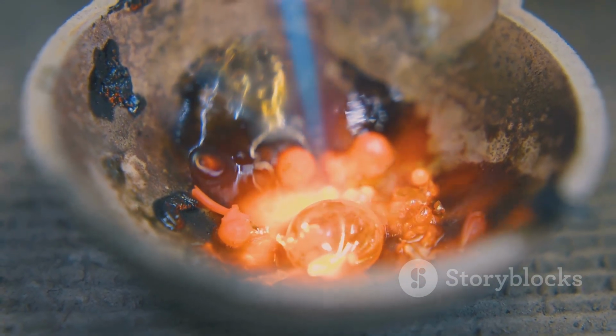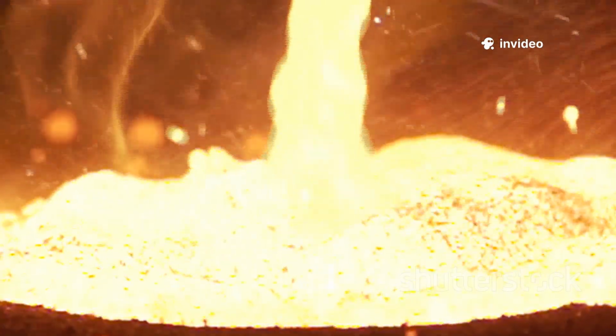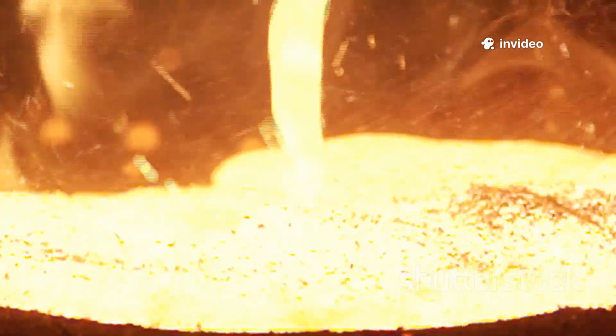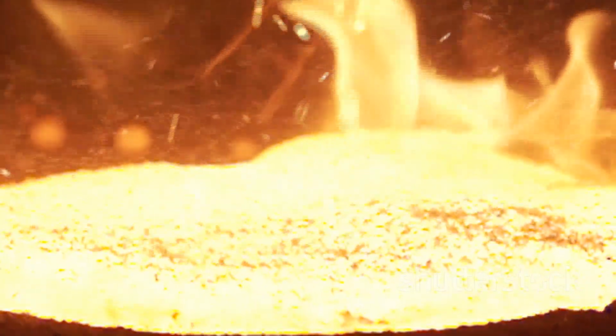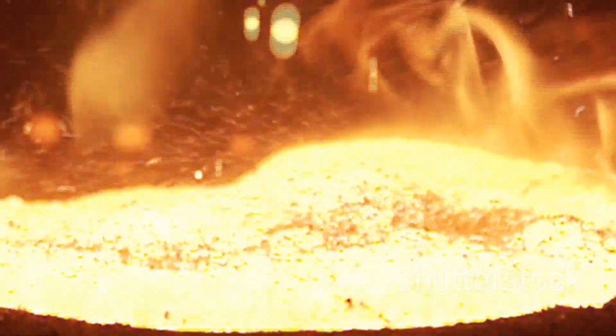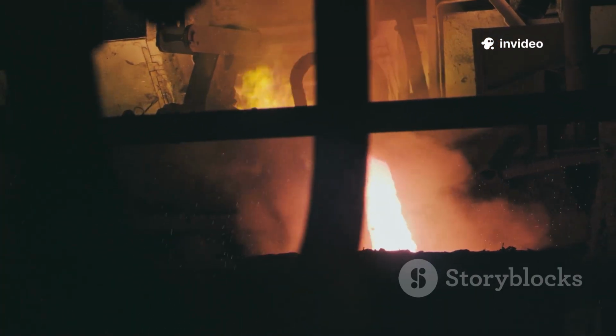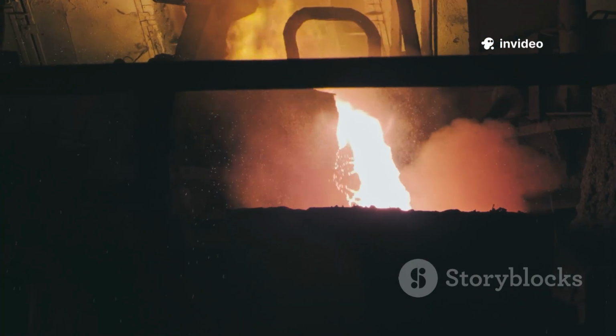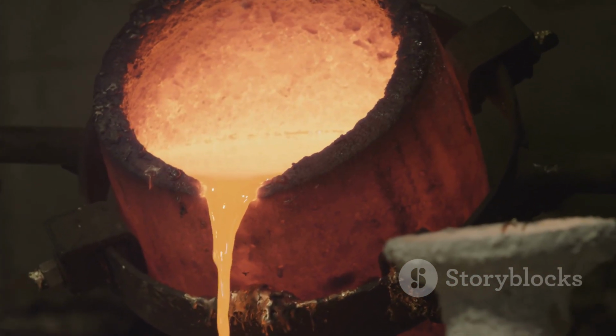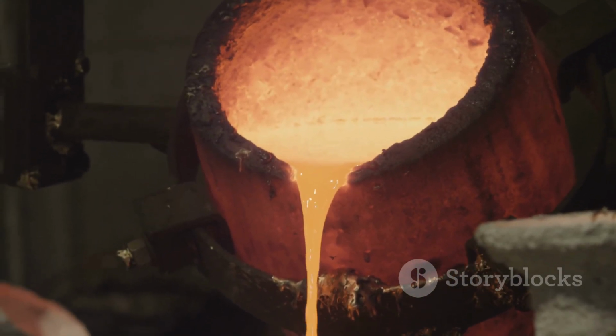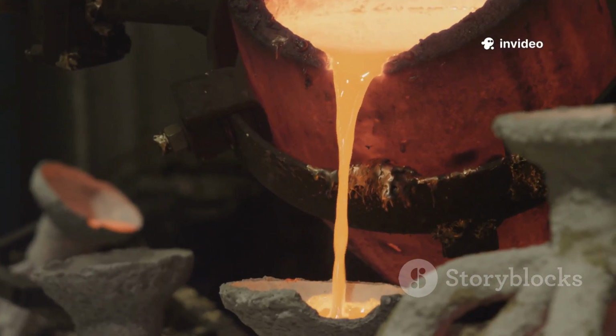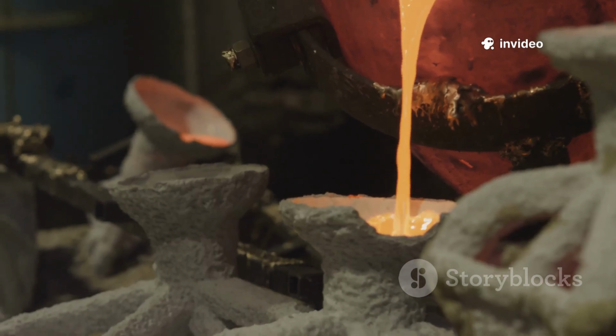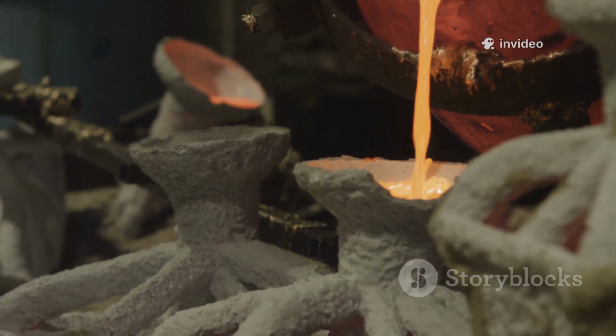Now comes the most dramatic part, the smelting. The gold powder and flux mixture is placed into a crucible, a special pot made of materials like silicon carbide that can withstand incredible temperatures. The crucible is then placed inside a furnace. These furnaces can reach temperatures of over 1,200 degrees Celsius, about 2,200 degrees Fahrenheit. That's actually hotter than volcanic lava. Inside this inferno, the gold and other metals melt into a glowing liquid pool. The flux does its job, binding with the impurities and causing them to rise to the surface, forming a layer of waste material called slag.